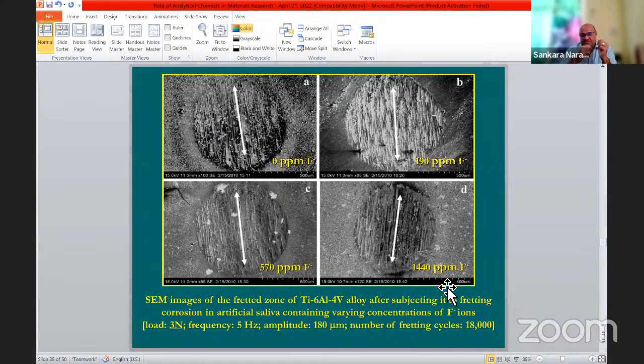So what happens in artificial saliva containing fluoride ions, how much is it degraded? That's what we analyzed. It's a small amplitude vibration. The total length is about 180 microns again. This is the damaged zone. We took SEM images, but we could not understand much from the SEM. We could see there is some damage, but we could not understand the mechanism of degradation. We varied the concentration of fluoride from 0 ppm, 190 ppm, 570 ppm, and 1440 ppm.